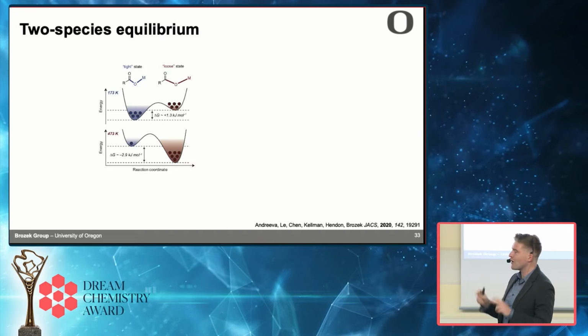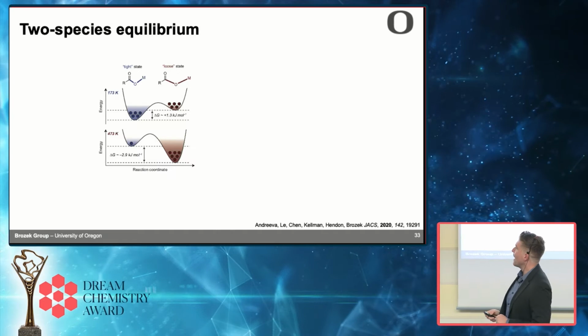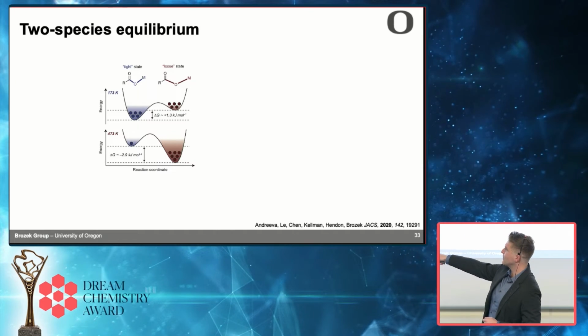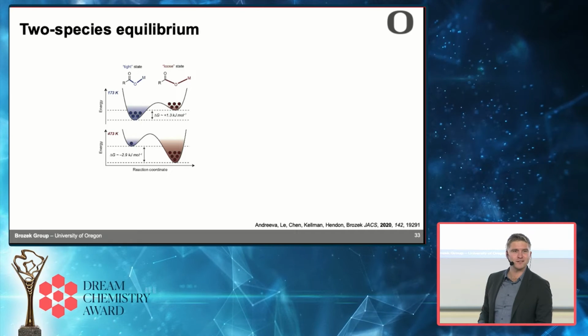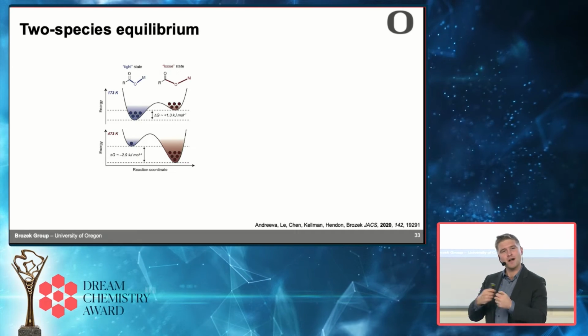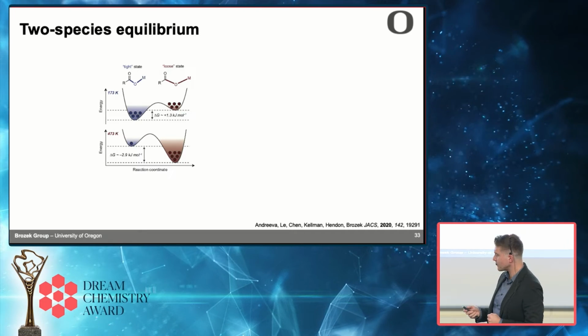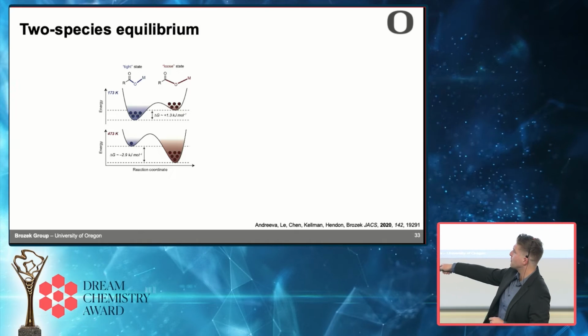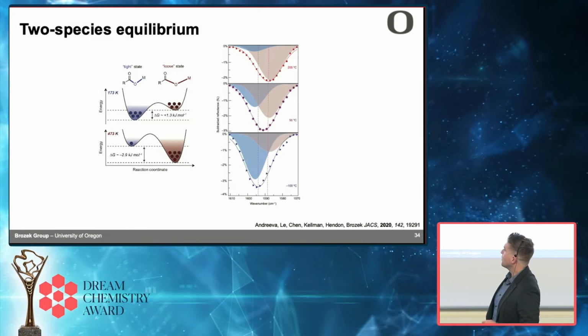We call this the tight state, okay? And then if you heat up the material, we figured that you would access a whole different collection of metal ligand conformations where the bonds are a little bit weaker, okay? And when you heat up the material, those become preferred. Well, this shows up in the data.